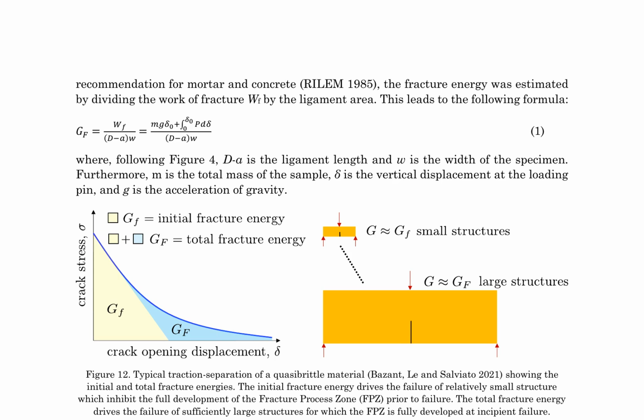Estimating fracture energy in quasibrittle materials, such as wood, is a complex task. The authors employ the RILEM recommended approach, dividing the work of fracture by the ligament area, to calculate the fracture energy, GF. This is expressed by equation 1, where D-a represents the ligament length, W is the specimen width, m is the total sample mass, delta is the vertical displacement at the loading pin, and g is the acceleration of gravity. While this approach is an approximation, it overcomes difficulties associated with estimating fracture energy from the rate of elastic potential or using the J-integral.